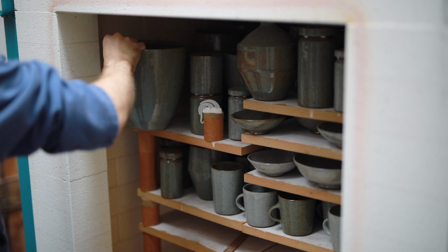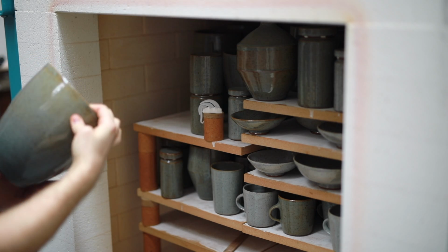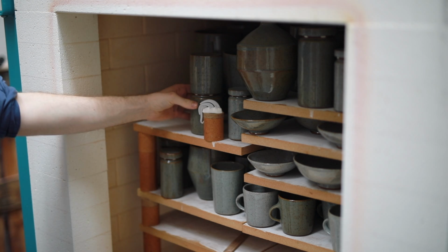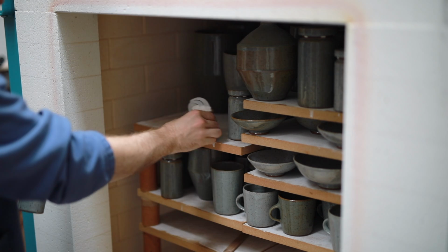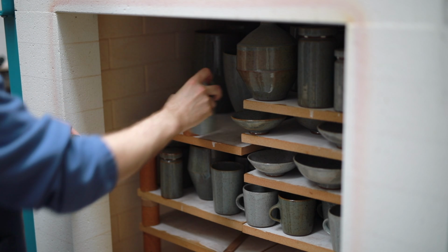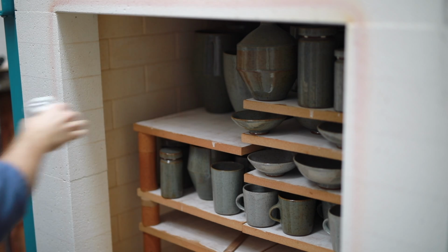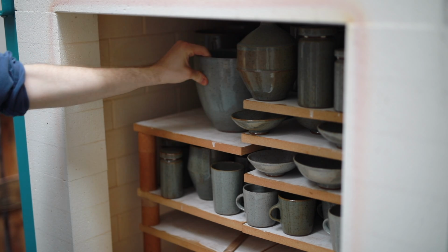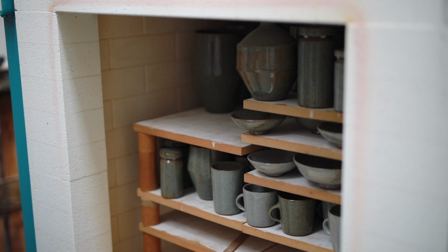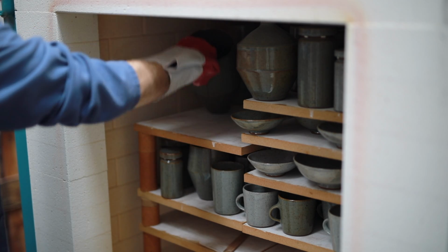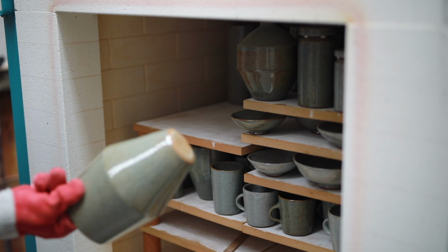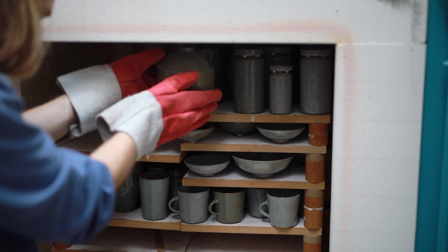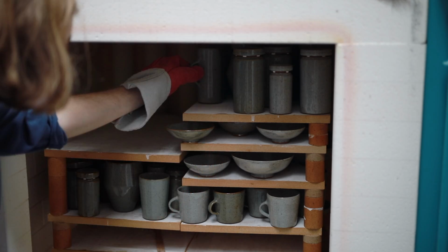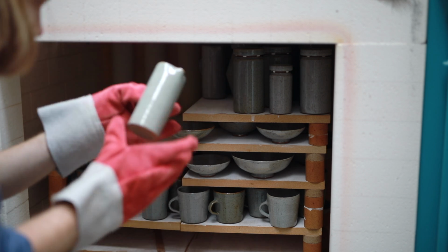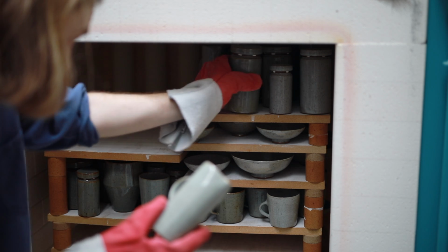I'll then take out each pot one by one, inspecting each as I go. In the middle you can see those 3 little white bent-over spikes. These are the cones I was looking at through the spy holes. These are what really tell me what's going on inside the kiln during the firing, as they measure heat work, which is heat over time, whereas the digital pyrometer simply tells you whether the temperature is going up or down. All in all, I can fit around 150 pieces in this kiln per firing, depending on their size of course.